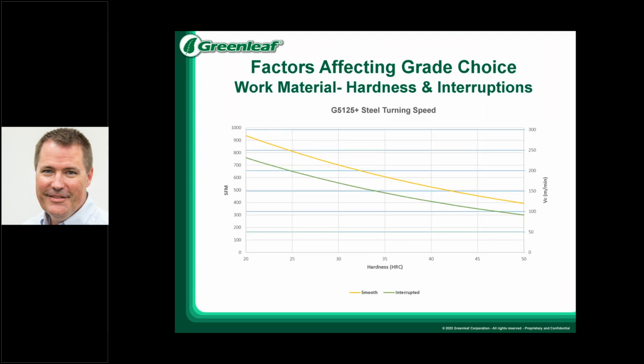Charts like this we use when considering hardness. You can see the hardness scale along the bottom axes there, and then surface speed referenced on the vertical axes. Whether the material is cutting with clean, smooth surface or in interruptions are also considerations. You can see the two color lines that we use here, the yellow and the green, just showing the green would be for interrupted, where you will want to reduce cutting speed slightly. And as you move from the lower hardness on the left to the higher hardness on the right, you can see the speed will drop. This is because of the heat that's generated when cutting.